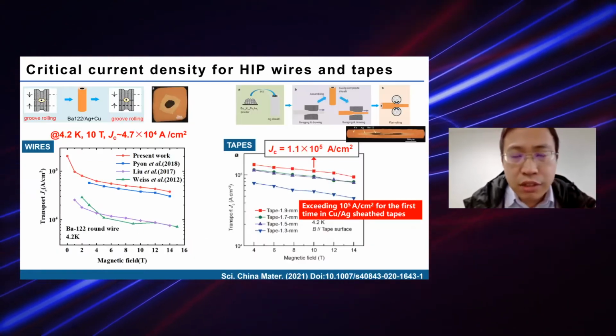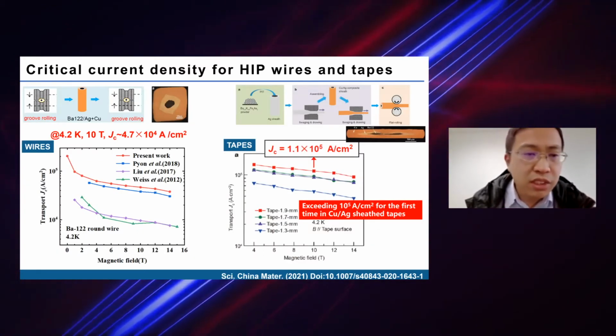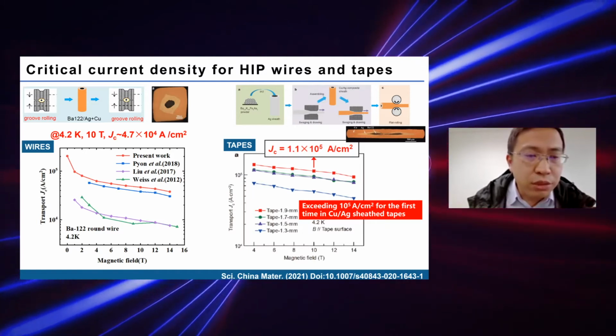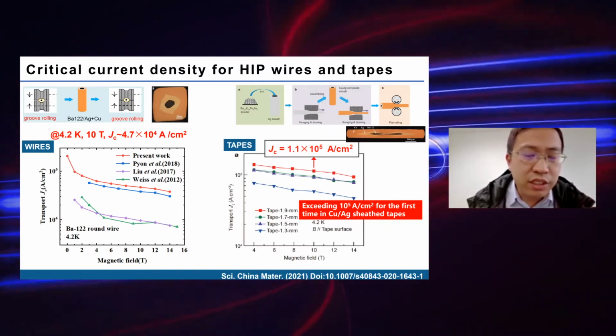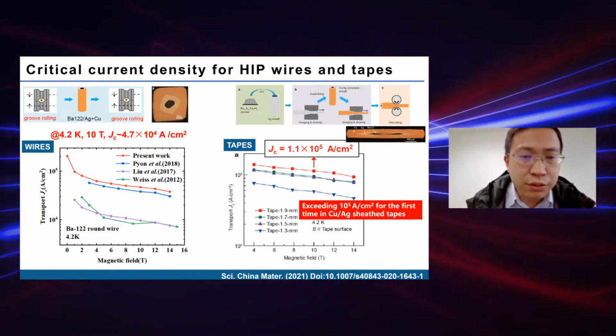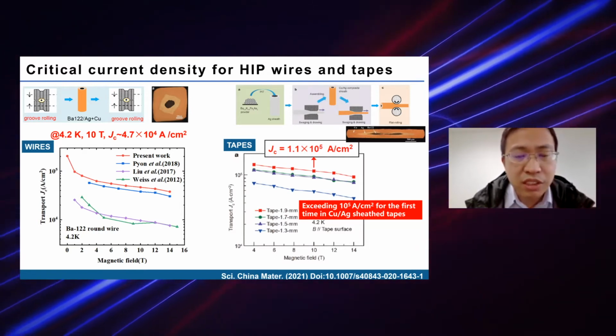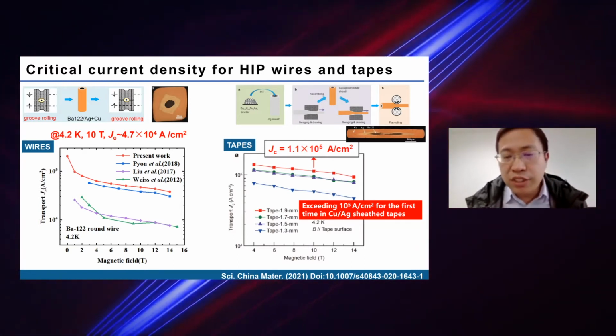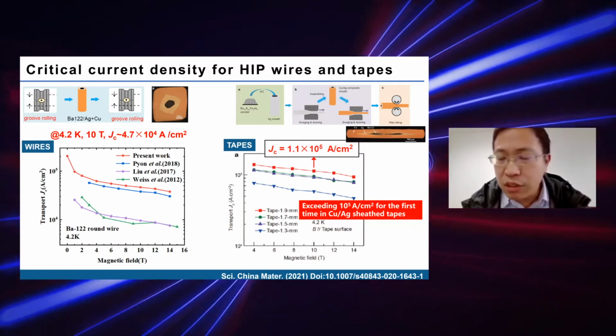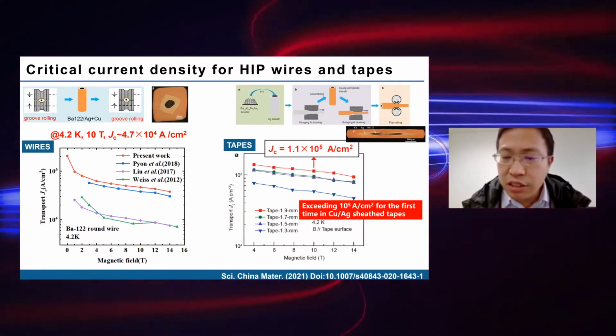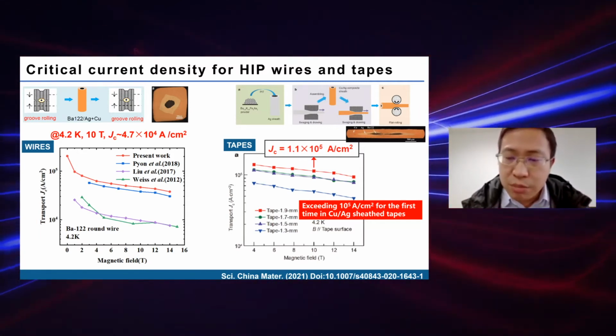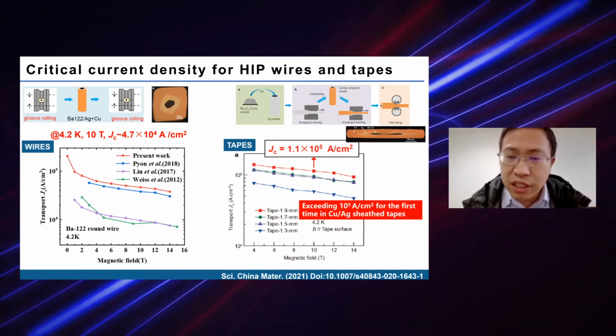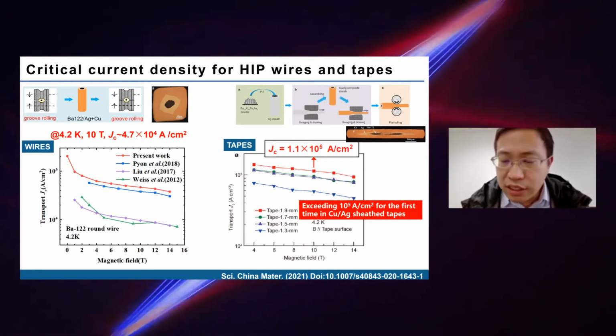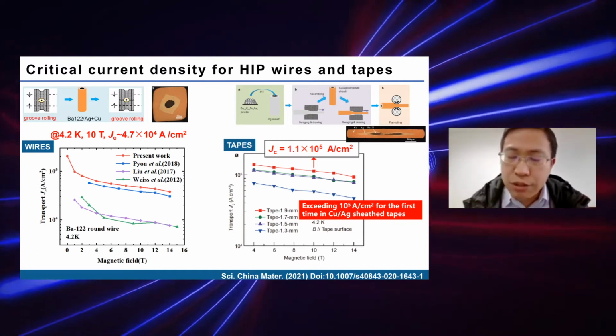And here are our best wires and tapes. At 4.2 Kelvin and 10 Tesla, the Jc of the round wire is 47,000 amperes per square centimeter. And for the tapes, because of the increased c-axis texture, the Jc at 4.2 Kelvin and 10 Tesla exceeds the level for practical applications.